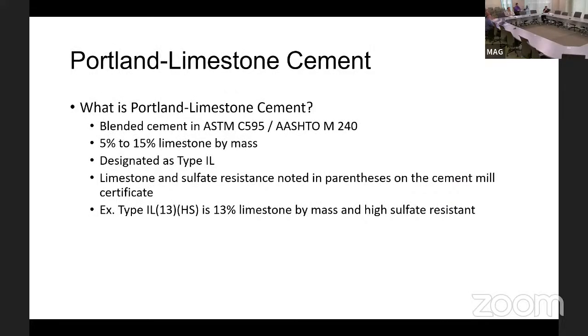So what is a Portland limestone cement? It's a blended cement, ASTM C595. It has a minimum of 5% limestone to a maximum of 15% limestone. Similar to ASTM C150 cement, which is also known as OPC, but OPC C150 cements have a maximum of 5%. So this just picks up with a higher replacement, giving you that enhanced lower CO2 footprint. The Portland limestone cement would be considered Type IL under the C595 designation, and limestone and sulfate resistance is going to be reported on the mill cert. So here's an example on a mill cert: type IL (13) (HS). The (13) designates the percent limestone in the cement, and the HS designates it's high sulfate resistant.